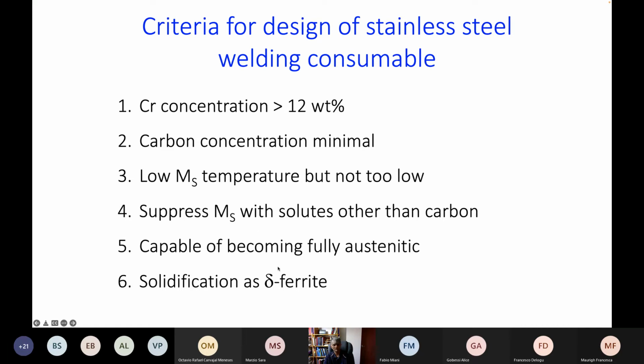But at some temperature, it must be capable of being fully austenitic. Now, if you add lots of chromium, then you can end up with some delta ferrite, which remains stable at all temperatures. So we need to balance the alloy so that it can become fully austenitic at high temperatures. And it's important that it solidifies as delta ferrite, because delta ferrite can absorb impurities, right? And therefore you stop hot cracking of the welding alloy. Whereas if it solidifies as austenite, austenite rejects the impurities into the liquid, and therefore you tend to solidify the liquid at too low a temperature, and you get hot cracking developing as the weld pool cools.